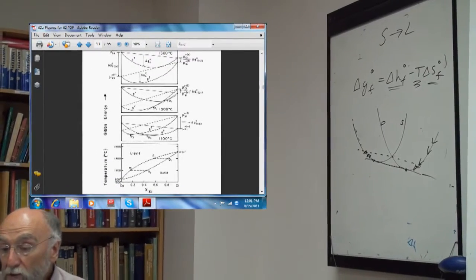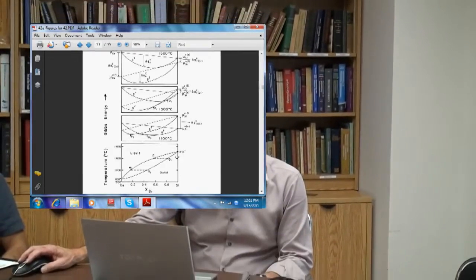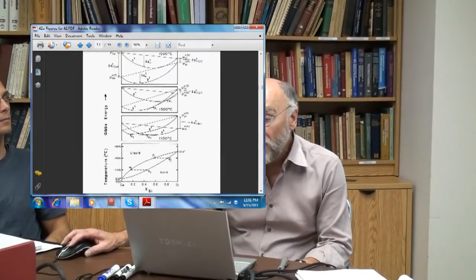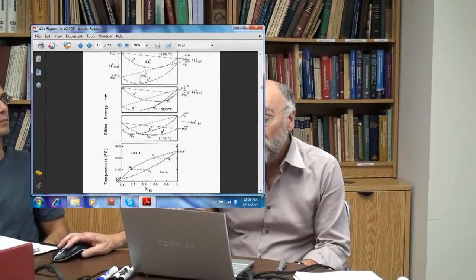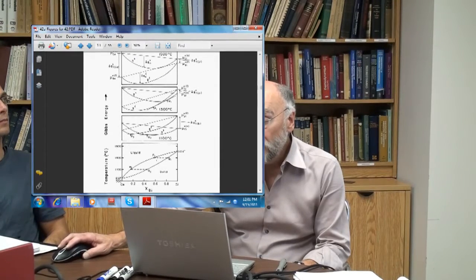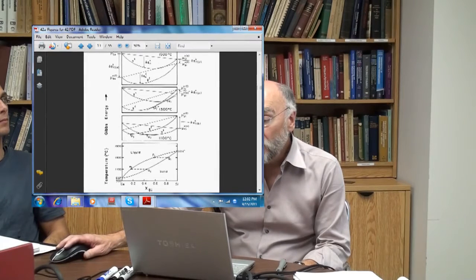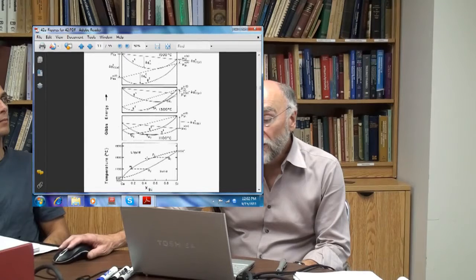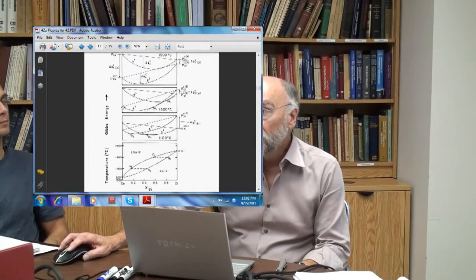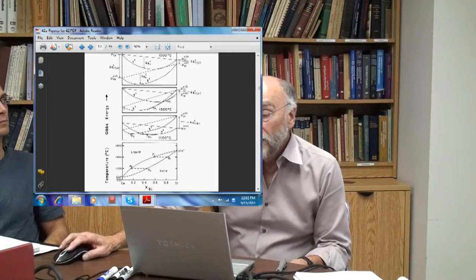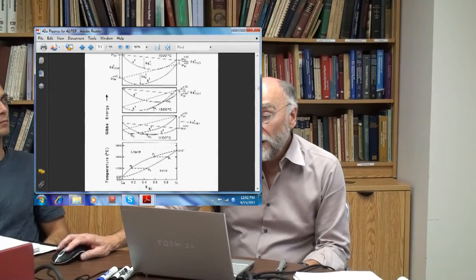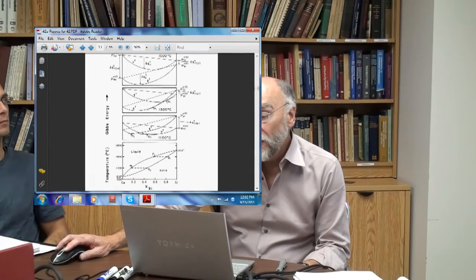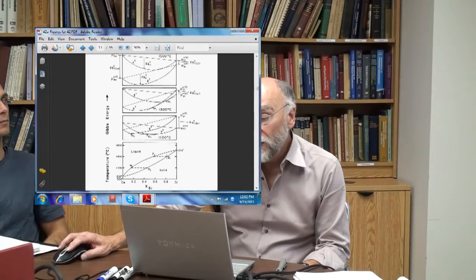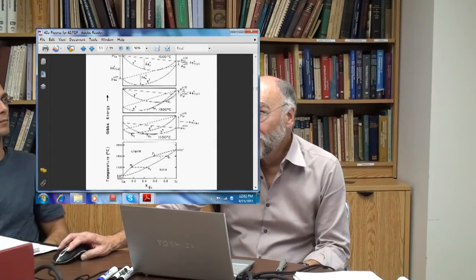As you start over here at 1300 degrees, you start with pure silicon, you move across, you have one solid phase, as the Gibbs energy of the solution follows this line. Then you have two phases, solid and liquid, as the total Gibbs energy follows the straight line between Q and P. And then, as you continue further, you continue up the liquid curve here. As you go from Q1 to P1, just by mass balance, the amounts of the phases change. At Q1, you have 100% solid and no liquid. Here you have 100% liquid and no solid. If you're exactly halfway in between, you have half of one and half of the other. And that's the lever rule.